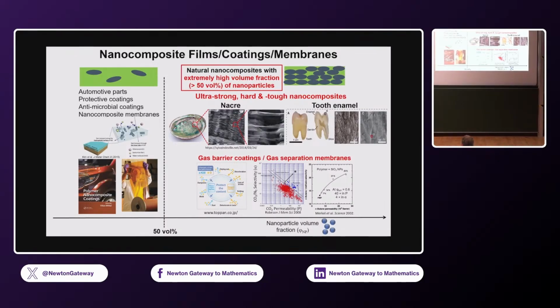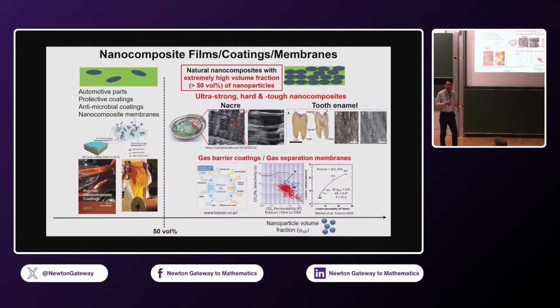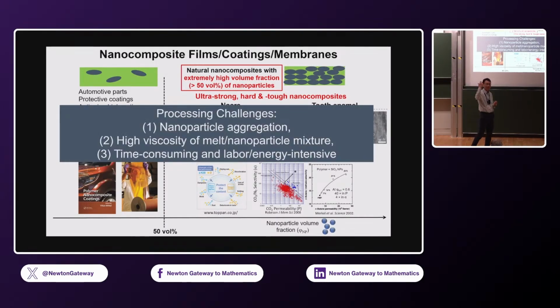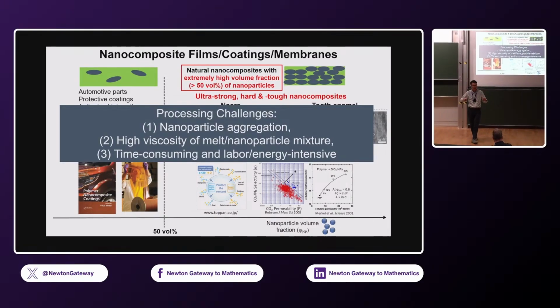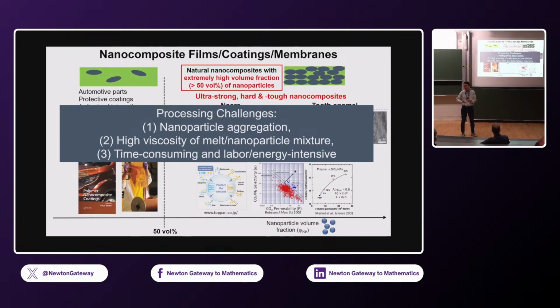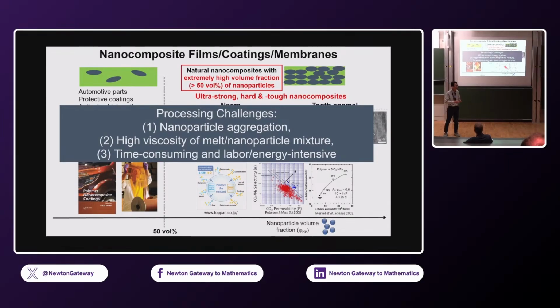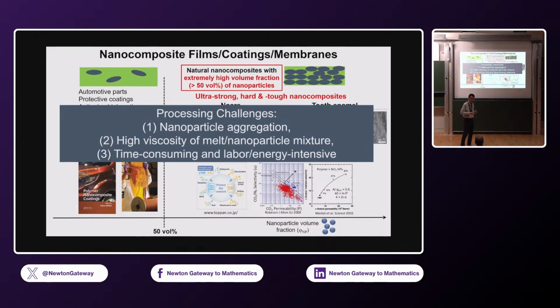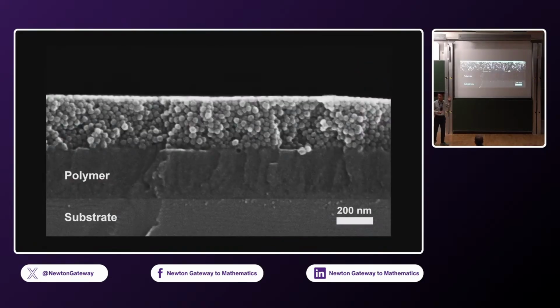You can also imagine making materials that have high gas barrier properties. The challenge with making these materials is that when you try to add high concentrations of nanoparticles into a polymer matrix and try to process these, the viscosity is extremely high, so the processing becomes very, very difficult. Okay, so that's why it's not so easy to make composites that look like these. So we wanted to see if there is a way to get there without using these very labor and energy intensive processes. So this is where we start.